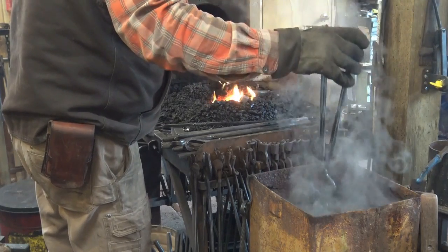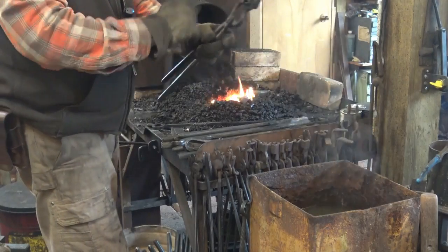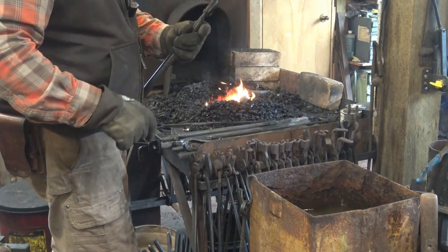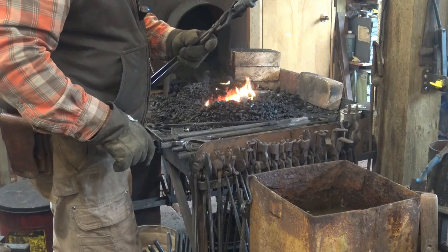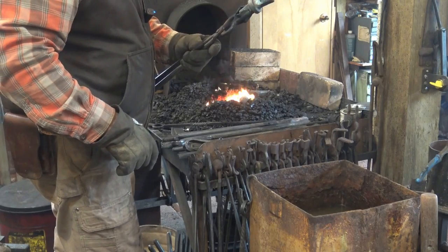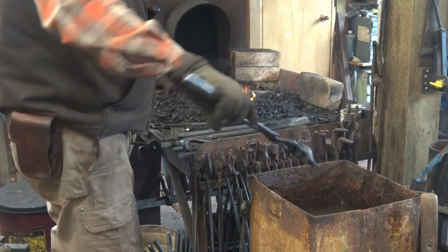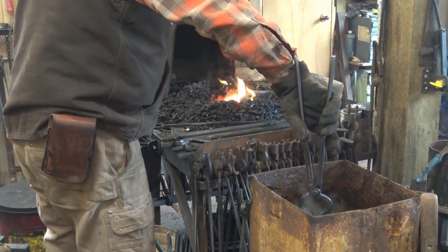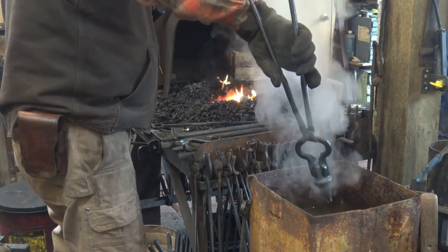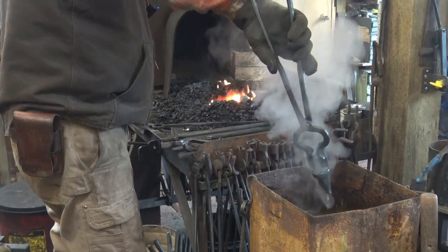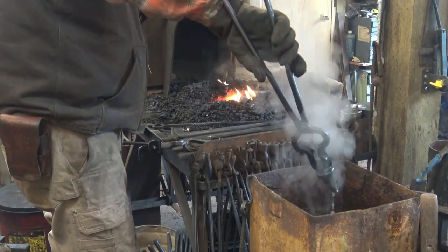Slowly kind of work it back in. You don't want to hold it at one level because you can create what they call a water crack. For that reason, because you cooled off right at a set line, you want it to transition and go from maximum hardness to maximum softness over an area.